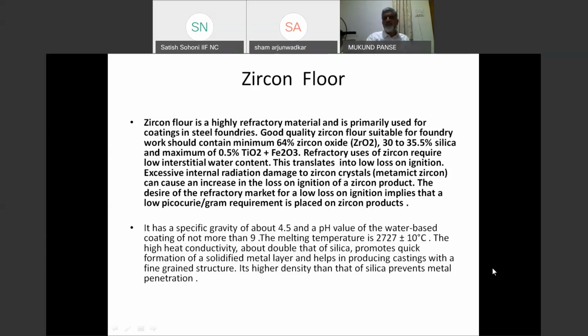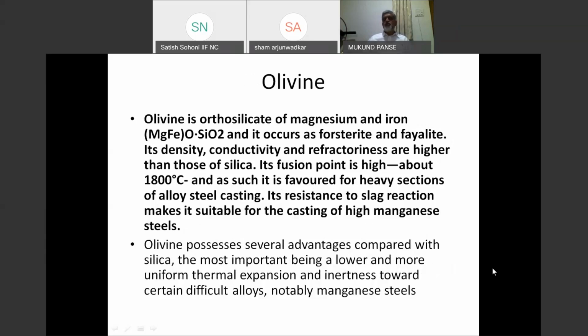Now this is used in mixture with some other refractory materials. Second is olivine. We have seen olivine has good chemical resistance (inertness) with manganese steel, and this is mainly used for manganese steel and some other heavy application. Again, the chemical composition is to be checked properly. Its thermal expansion is slightly lower than silica, but it is not as good as zircon. Fusion point is high, 1800. It is more than silica, but lower than zircon. But this paint is used for manganese steel.